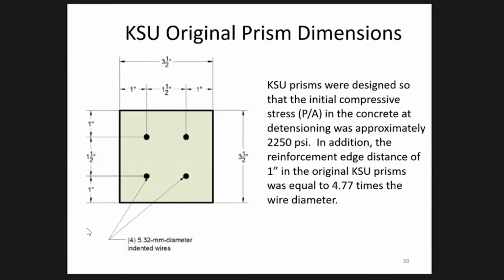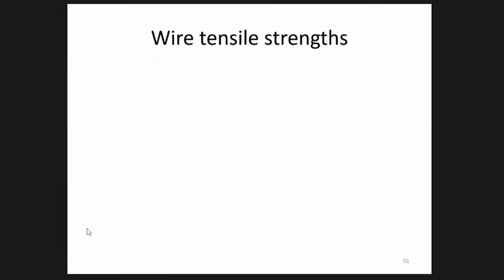Also, the wires were 1 inch from the center of the wire to the outside, and these were 5.32 millimeter wires. So this distance, the 1 inch, was actually 4.77 times the wire diameter. So we kept those parameters the same.